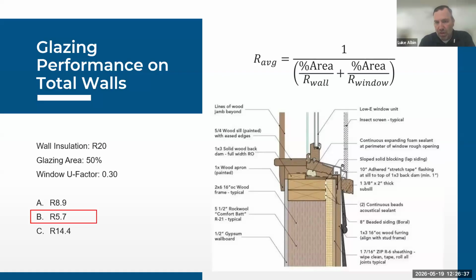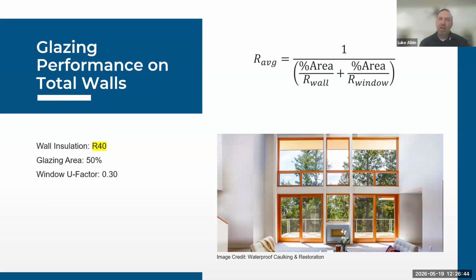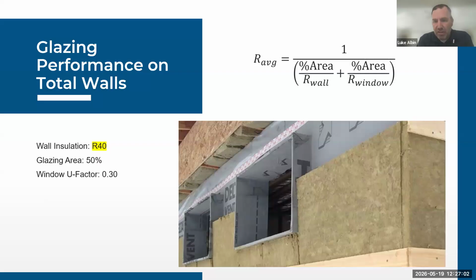Here's just a typical example of an R20 wall, detailed out. But we want to get better performance out of our wall assembly. So what we're going to do is use R40 wall insulation, same 50% glazing area, same window U-factor of 0.30. So when we do that, you see here's some extra material, extra labor, extra time to detail the R40 wall versus the R20 wall. A lot of different factors go into building this insulation out, as you all have probably run into. So we've done all that, and now our assembly is 6.2. We've gained a whopping, not so whopping, I should say, 8% increase over 5.7.